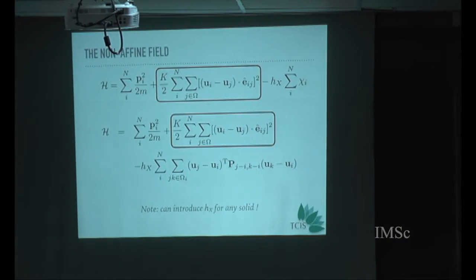So now this is really it. If this non-affine parameter is just dependent on particle positions, I can simply define a field which is conjugate to it and attach it with the Hamiltonian. Okay. So think about this. You have displacements and you can look at the affine part of the displacement. And then you can add a term in the Hamiltonian which is the affine part of the displacement multiplied by the field. This is just stress because the affine part of the displacement is just strain. So this will be like this extended Lagrangian, where you add to the Hamiltonian a stress into strain.